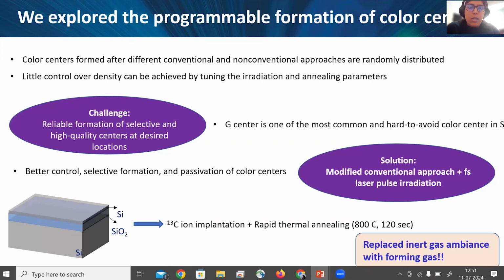So we need to come up with a new approach by which we can decide where we need these color centers. Also, when you use different approaches, what we have been seeing is that you normally make the G center, which is among the most commonly formed color centers in silicon. So you do any sort of irradiation, be it ion implantation or electron or proton irradiation, you end up getting the G center. And that is also one reason why we cannot easily make other color centers, because we are flooded with the G center. Now, what we have recently done is modify the conventional approach, and also include femtosecond lasers in the picture to locally manipulate the formation of these color centers.